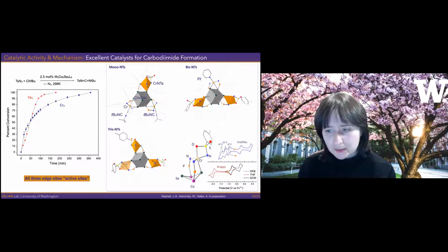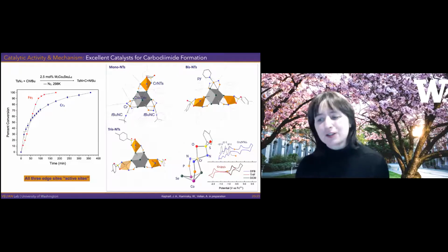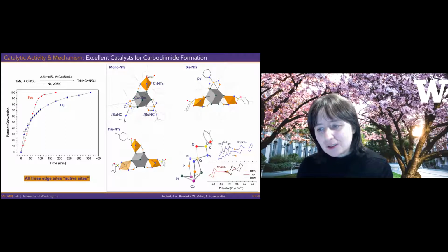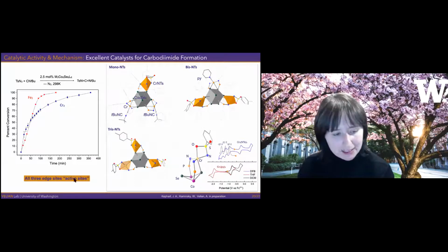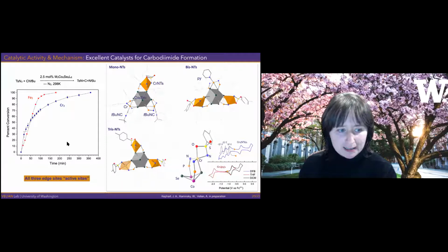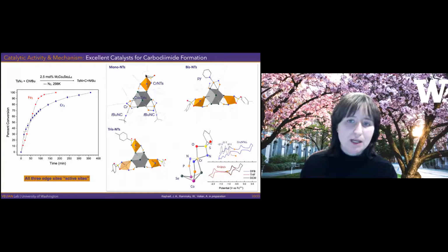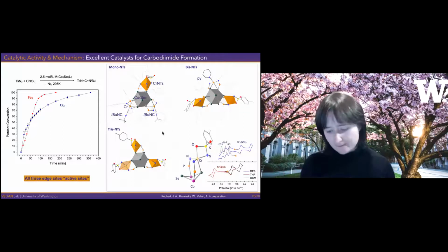This system is something that we are currently studying, and we're very excited about it because it also has this amazing electrochemical profile. So, an electronic structure that we can probe electrochemically, and we can in fact go from reducing what we think is the chromium-nitrogen multiple bond once, twice, and 3 times. So we're hoping the system is going to answer important questions about how the edge sites respond, and how transferring the first nitrene is different from the second to the third, because that might answer this question of allosteric effects on the cluster surface.